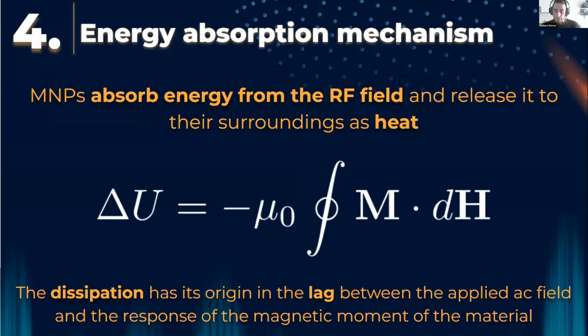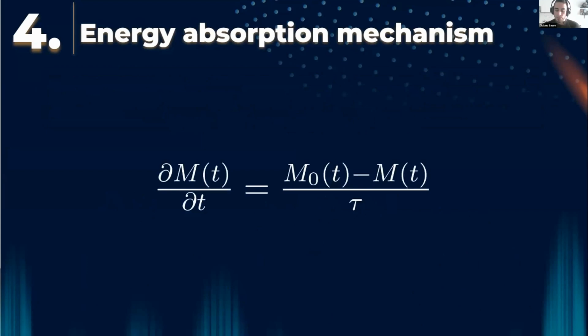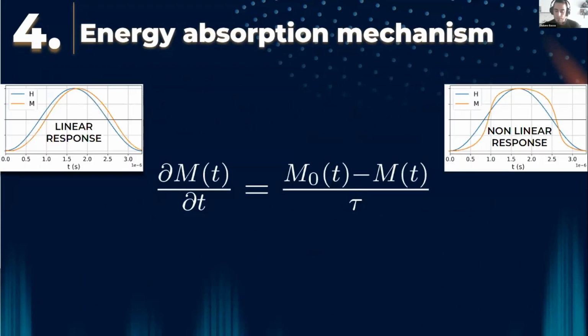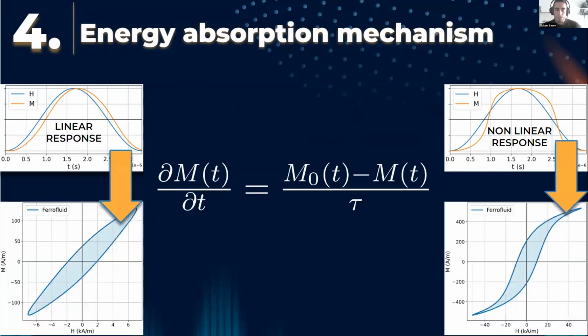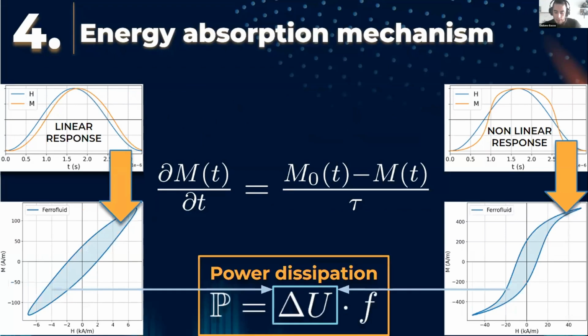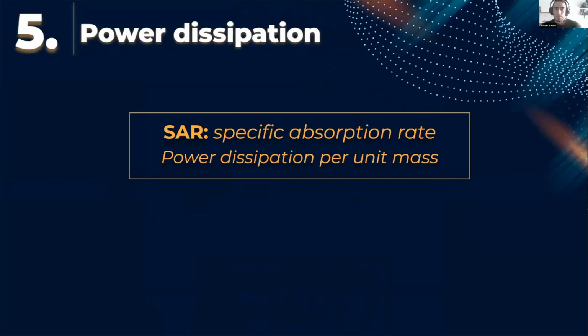The power dissipation has its origin in the magnetization lag in response to the applied magnetic field. This lag is characterized by the magnetization's relaxation time. We call it tau. So the key performance metric for this application is called specific absorption rate, and it is the power dissipation per unit mass of magnetic nanoparticles at a specific field amplitude and frequency.